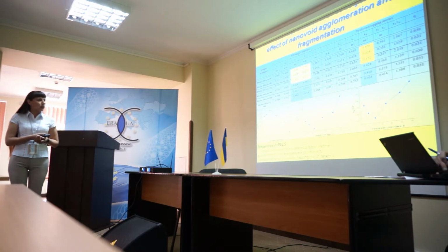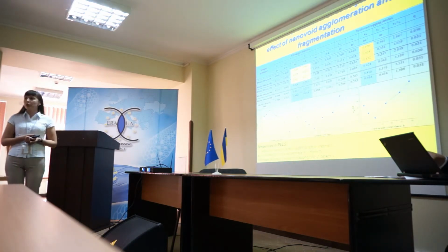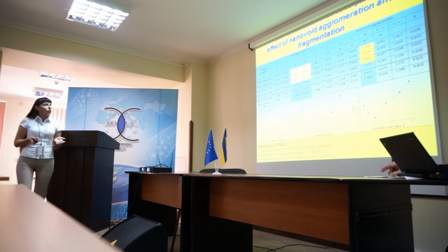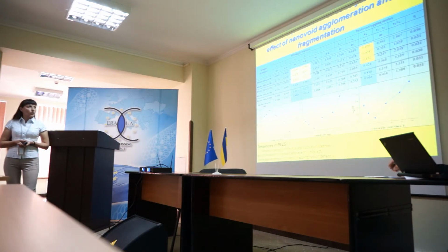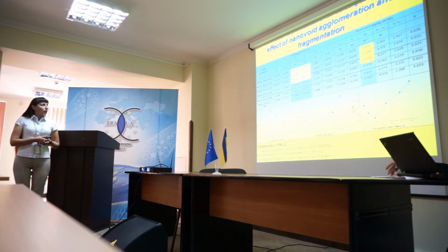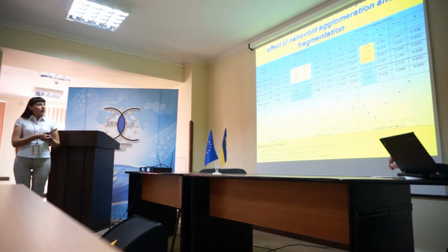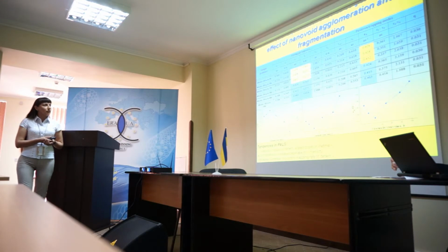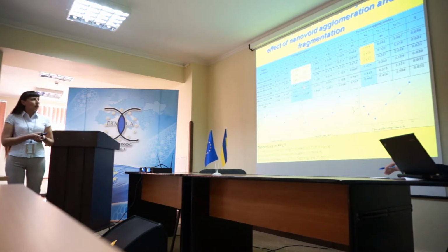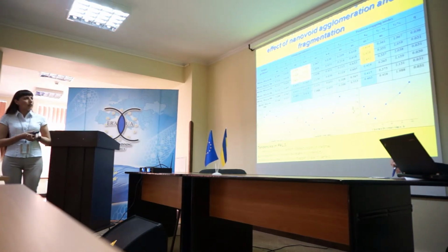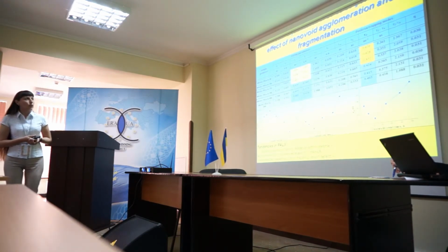You can see in this picture three main parameters for interpretation of the evolution of free volume in different solids. After annealing at 50, 80 and 100 hours, we have the inverse process. Tau2 decreases, intensity increases, and positron trapping rate in defects also decreases.